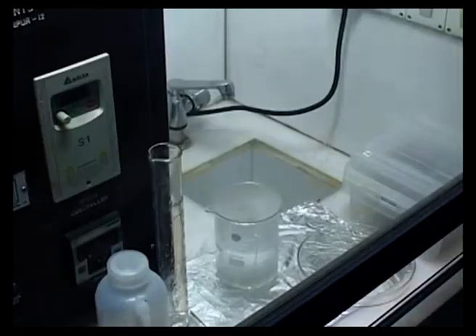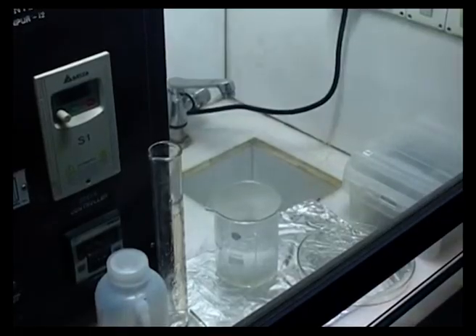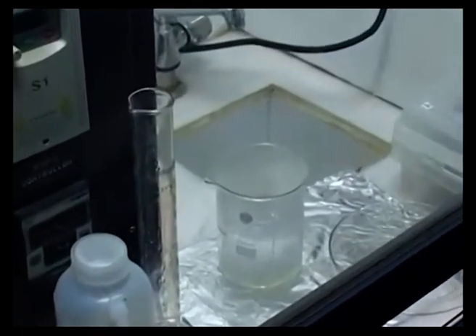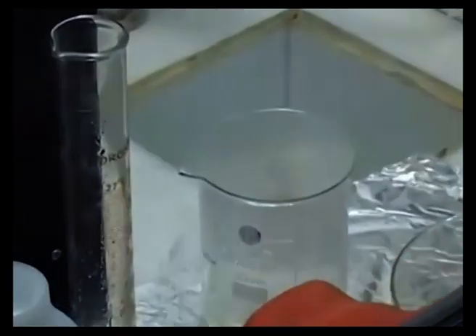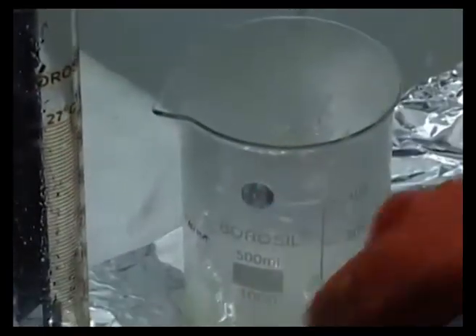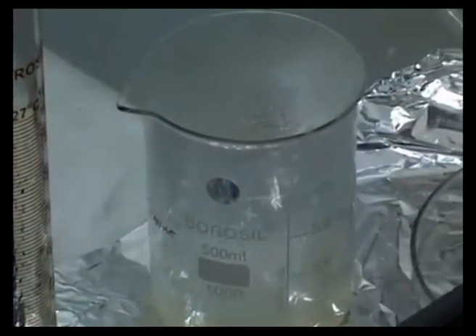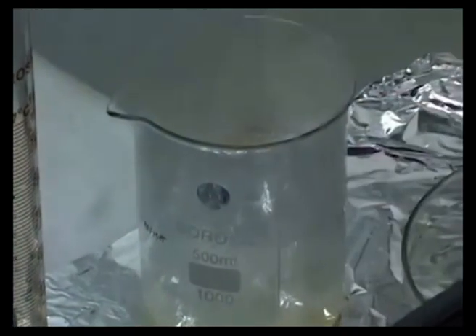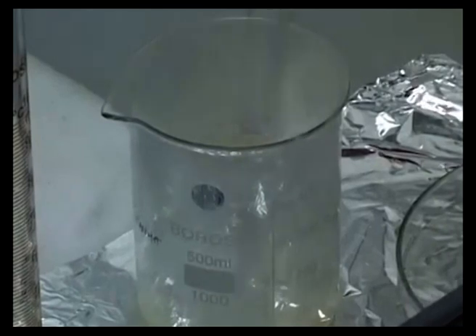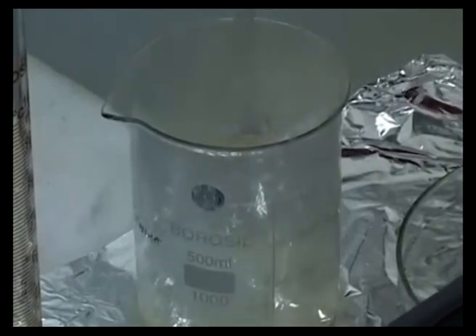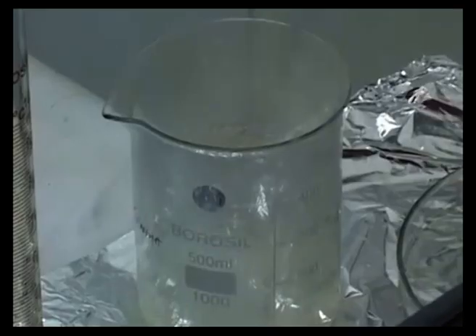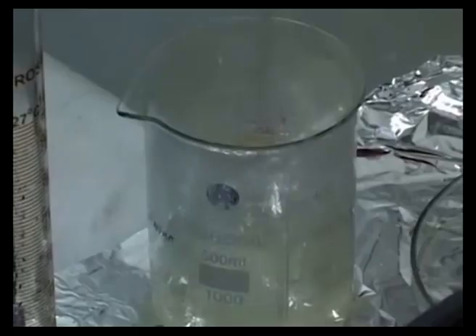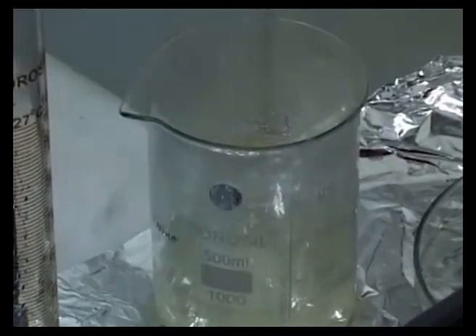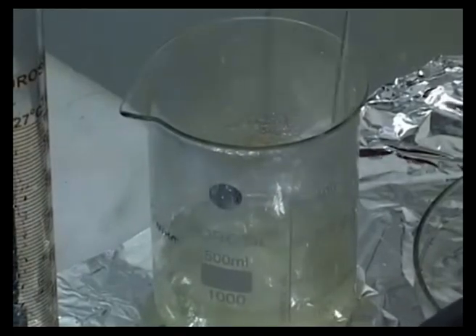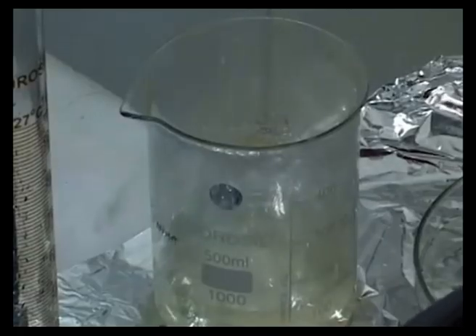So as you can see, the fumes are slowly settling down because essentially it is a very, very highly exothermic reaction. So what you do now is to actually use a glass rod and stir the solution very well so that the mixing between the hydrogen peroxide and sulfuric acid takes place. And then once this is ready, and mind you, this is a very hot chemical, you have to be careful while even pouring it into the separate petri dish, as I'll just illustrate in the next step.